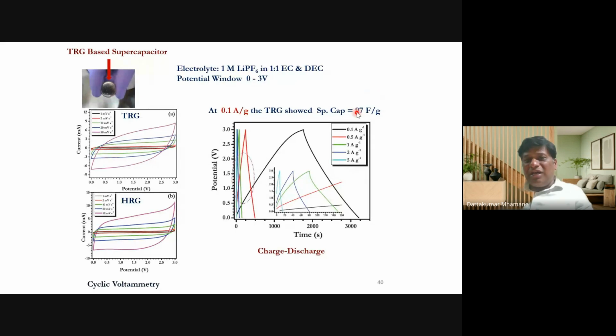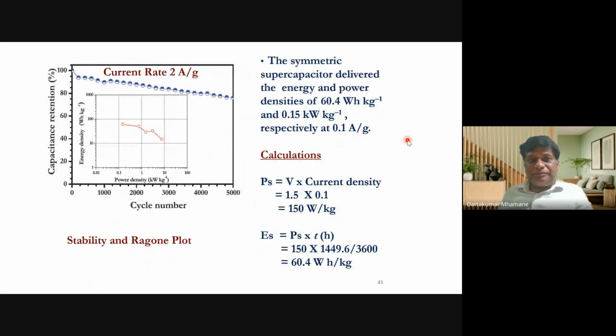So of course the results are very low, but we used around 5 milligram of our active material. People generally use 1 milligram, 0.8 milligram, and show their result in the paper. But in this device, we used around 4 to 5 milligram of sample, which is very high, and because of that resistance increases, and as resistance increases, the charge storage capacity decreases. Still, these are good results, I can say. And this is the Ragone plot. I told you, you can see our material lies in this energy and power region.